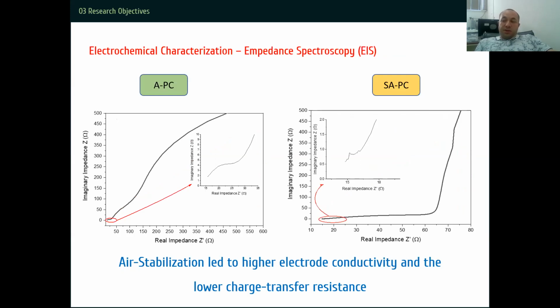In the EIS spectra, in impedance spectroscopy, the high frequency region gives two messages. First, the real axis intercept represents a combined resistance containing intrinsic resistance of electrode material, ionic resistance of electrolyte, and contact resistance between the electrode and the current collector. And second, the radius of a semicircle is indicative of the electrode conductivity and the charge transfer resistance of electrode material, which is very important. In our experiments, it can be seen that the charge transfer resistance is very low in SAPC sample compared to APC sample. In addition, the electrode conductivity, which is essential for high capacitive performance, is higher in SAPC sample.